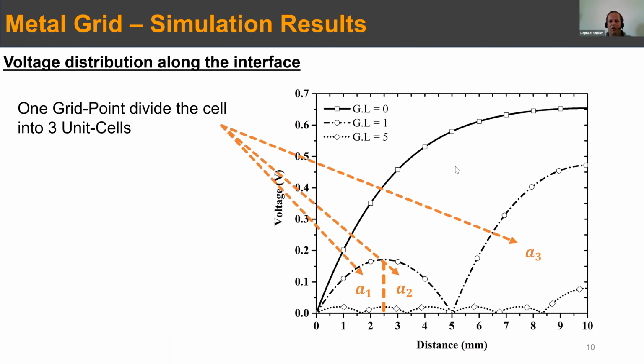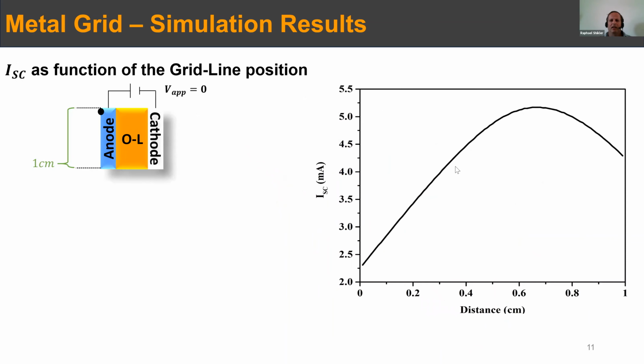And what we found out is that if you have one grid line, let's look at this example. The grid line is positioned at 2.5 millimeter. Then basically you have a division of the entire 10 millimeters into 3 cells. One between 0 and 2.5, one between 2.5 and 5, and one from 5 till the end. And the first 2 cells are symmetric, while the third one is obviously larger, so you have a larger development of voltage on it. And this is what gives you the idea of how you can divide the cell if you really like to achieve the maximum. If you have just one line, you can put it anywhere across the anode. The maximum will be at 2/3. And this was valid both experimentally and from the simulation.